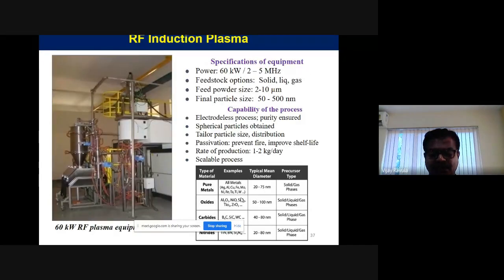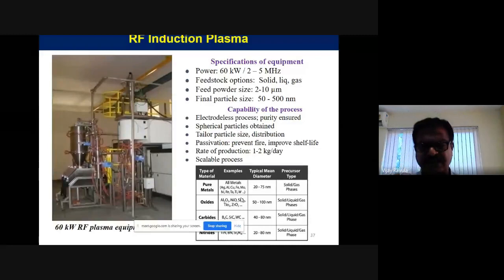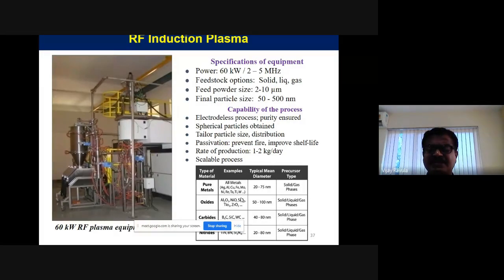And another process is large scale nano powder production. This is called RF induction plasma. This is all a physical process. One of the processes is you start with micron-sized powder particles, and then you directly vaporize the material because of the high temperature of the plasma. And when you get rapid solidification of those vapors, they result in the formation of nano powders.